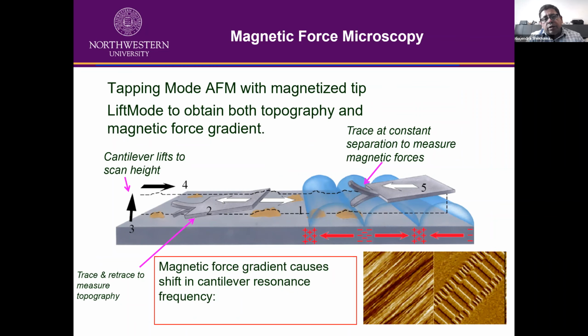This is also in the category of the family of functional AFM, where you can basically measure the magnetic properties, the magnetic gradient that causes a shift in the cantilever resonance. So here is a two-pass approach where we use the lift mode. Lift mode basically allows imaging of relatively weak but long-range magnetic interactions while minimizing the influence of surface topography.